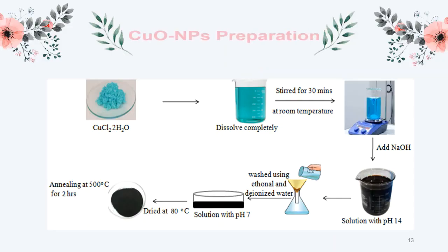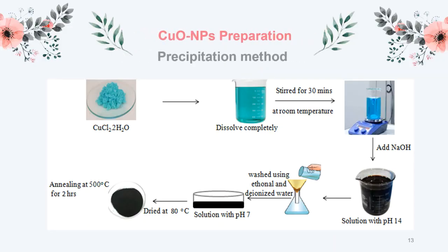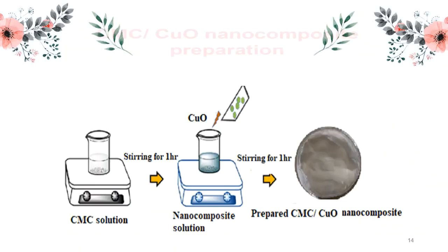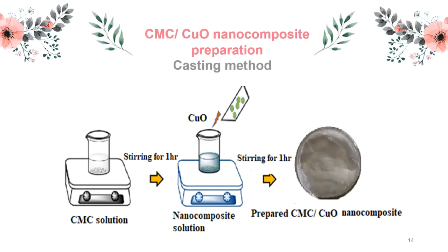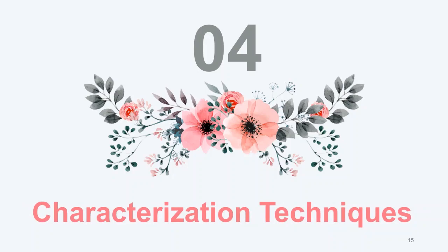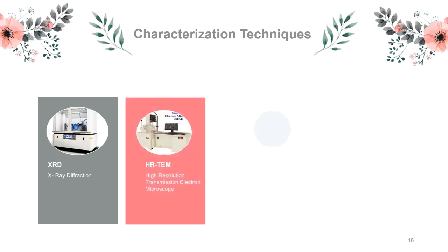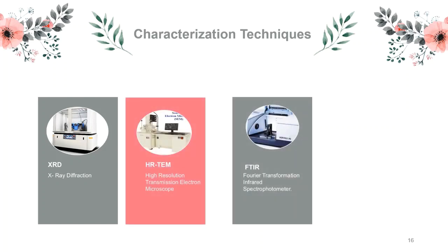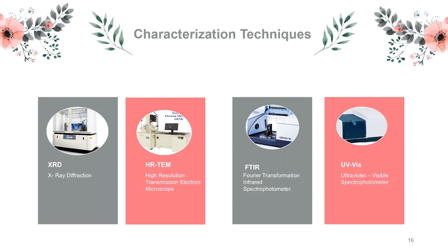Preparation method. Copper oxide nanoparticles were prepared using the precipitation method by following the steps presented in this figure. Nanocomposite films based on CMC and copper oxide nanoparticles were prepared utilizing the casting method as presented in the following scheme, and this film presents the final form of the CMC copper oxide nanocomposite sample. Characterization techniques. The produced nanocomposites will be characterized utilizing XRD, high resolution TEM, FTIR, and UV-visible spectrophotometer.